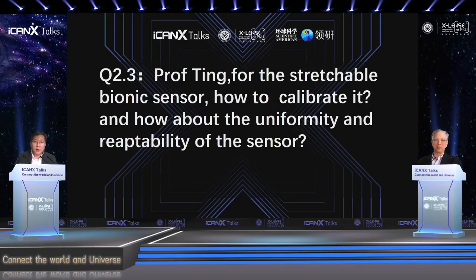So we have the force gauge in our lab to calibrate these flexible or stretchable sensors, which can stretch at different states while measuring the electrical signal changes. To achieve the uniformity and the repeatability of the sensors, for the repeatability, you have to make your device very reversible. So you have to rationally choose your materials and make the reversible response of your sensor first. And uniformity is a very key issue for the applications. Then you have to make a very uniform dispersion of your nanomaterials, and develop your printing process to make highly uniform composite films. Then you can get the uniformity of the sensors.